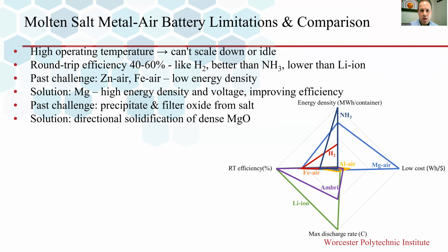So when we compare it to other battery and other technologies, I've got multiple technologies here. First, we have hydrogen and ammonia as potential fuels and fuel cells. We also have iron air batteries, aluminum air batteries, the Ambri battery, looking at the calcium shuttle with calcium antimony derived from liquid metal battery with a liquid metal anode in that case, and also lithium ion. So lithium ion has the highest round trip efficiency and the highest potential discharge rate, but at the cost of the highest cost and the lowest energy density of these. The magnesium air battery has a very low cost, very high energy density, and good round trip efficiency, about 50%, which is comparable to the hydrogen and ammonia, better than ammonia, but at the cost of low discharge rate.